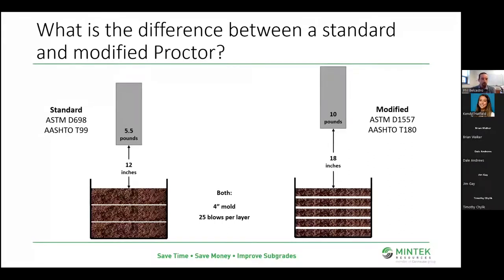They both use a 4-inch mold, unless there's 30% sample passing 3/4. We can get into some of the intricacies, but that's usually for aggregate base course. So really for soil, we're both going to be using a 4-inch mold, 25 blows per layer, but the different compactive effort comes from the weight of the hammer we're dropping, the height of the hammer, and the number of layers. Like I said, usually we're doing the standard, which is 5.5 pounds, 12 inches, 3 layers.